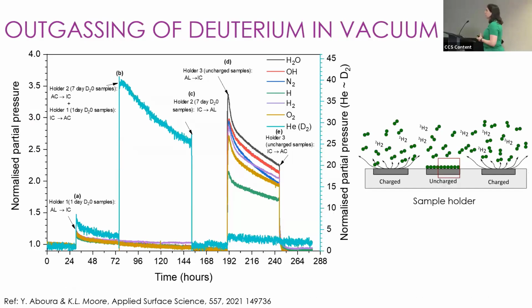The other issue, which we knew was probably going to be an issue, was the fact that, as I said, we don't have a cryostage on the NanoSIMS. And as I said, hydrogen in metals is very, very mobile. We were worried that we were going to lose a lot of our deuterium into the vacuum system before we could even analyze it. So what we aimed to do always was to try and charge our sample and as quickly as possible get it into the NanoSIMS under vacuum and start analyzing it.